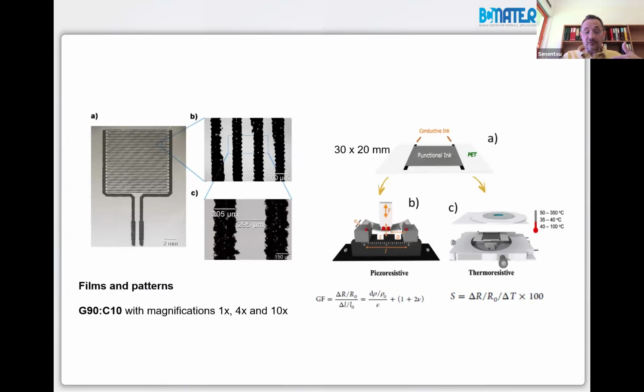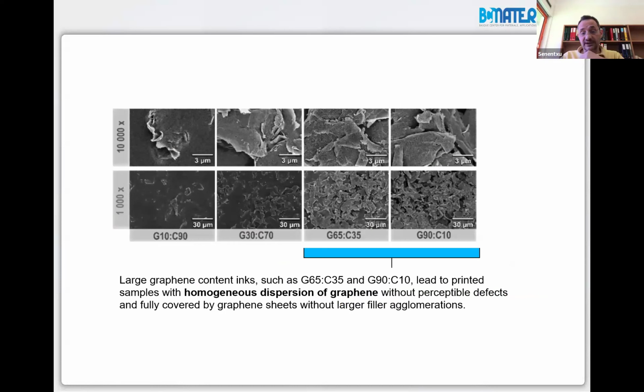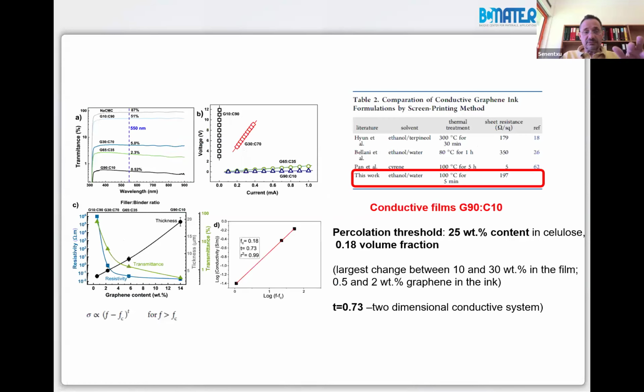Of course, depending on the rheology, the structure of the line that you obtain is better or not so good. Because we are not using any further materials than these three, but this is enough for the applications. It is great. And with 90% graphene oxide, we have conductive tracks, and as I say, by varying a little bit. You have here the printed lines, very compact, very interesting, independent of the graphene content. You have conductivity among the largest in the literature, all with environmentally friendly materials and with no further addition.